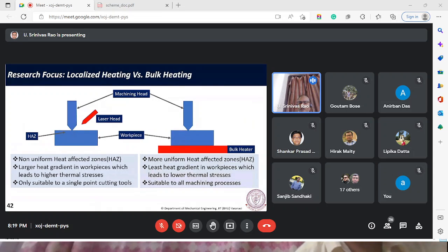However, there are some issues, as we have pointed out. Local heating creates a non-uniform heat affected zone, and then high thermal stresses, and this is if you are using a single point cutting tool, so the area in front of the tool may be heated in a better way. But with these issues in mind, what we have thought is, let us try with bulk heating.